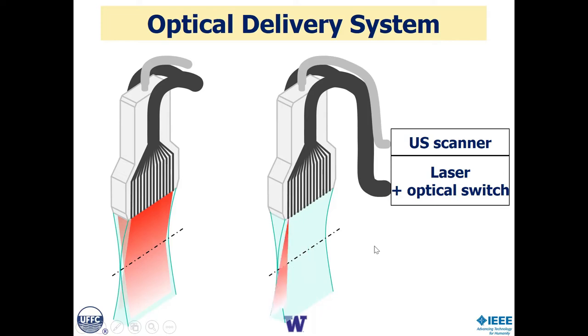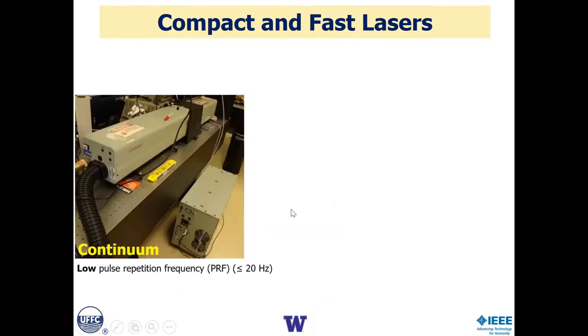We, in contrast, have worked with a fast scanning approach where we take a much smaller compact laser that can work at very high repetition rates though. And then instead of delivering to all fibers at once, we deliver to one fiber per firing. So in each firing, we're delivering light to a single fiber and rapidly scanning this across the imaging field. What does this do? What it does, first of all, is it changes this class of laser technology, these big, bulky, and slow lasers, to ones that look like this.